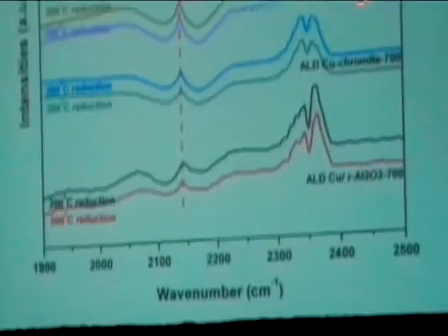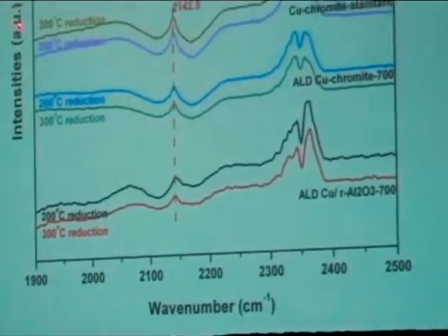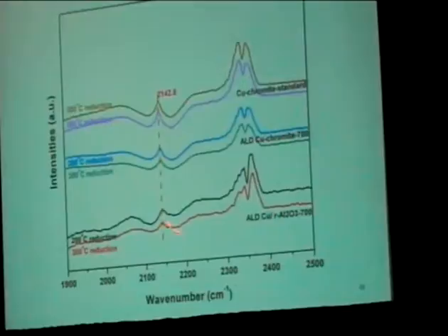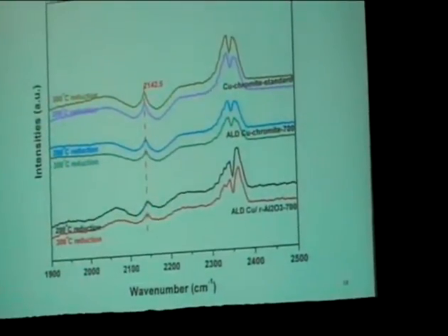One of the things we've looked at so far is the CO adsorption studies using FTIR. And you can see here's the copper chromite catalyst to begin with, reduced at either 200 or 300 degrees. You can see the characteristic peaks here. This is due to the chromium oxide, and here's the adsorption of the CO.